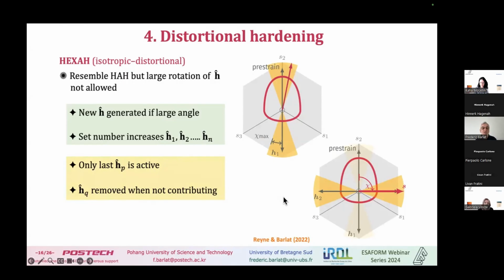And all the other ones tend to recover the isotropic hardening state, and actually they are removed when they don't contribute to the yield condition. So practically, we don't have so many microstructure deviators to handle at once. Also, each microstructure deviator is defined with the same coefficients, maybe not the same direction, but the coefficients to identify it or to evolve it are similar. So we don't have too much difficulty. We don't have more coefficients. That's what I want to say. The state variable evolutions are similar to HAH20. They had to be changed, of course, but the idea is the same as the HAH model.